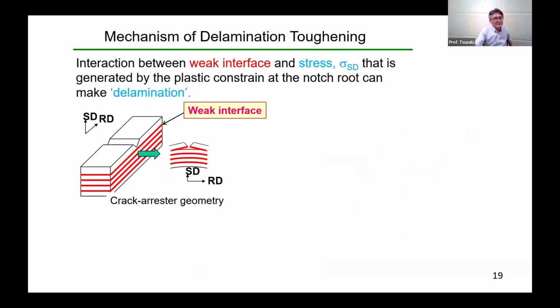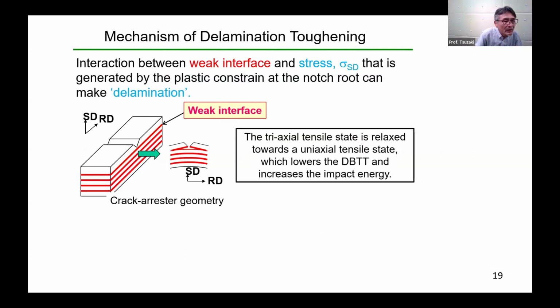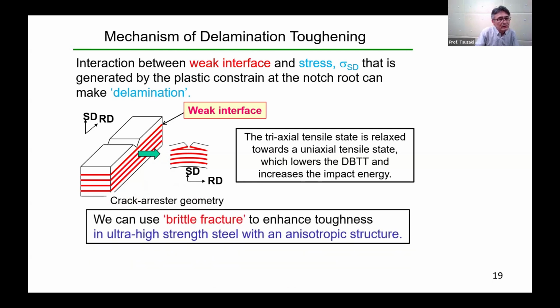We have studied the mechanism of delamination toughening. Interaction between weak interface and stress sigma SD, striking direction, that is generated by plastic constraint at the notch root can make delamination. When the delamination with a crack arrester geometry occurs, as shown in the left figure, the triaxial tensile stress state is relaxed toward a uniaxial tensile state, which lowers the DBTT and increases the impact energy. This means that we can use brittle fracture to enhance toughness in ultra-high strength steel with an anisotropic structure.